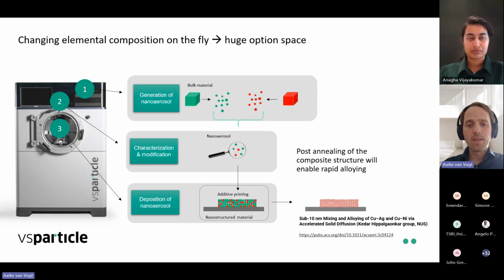One additional comment I would like to make is that we can print these nanoporous layers on almost any substrate. And the reason is that we build up these layers by using very small 2-3 nanometer particles, which by themselves have a very strong van der Waals force. And this strong van der Waals force will make them stick to any surface, but also to any of the other nanoparticles that you print. So we can print these nanoporous layers directly onto polymeric membranes, onto silicon wafers, onto copper foils, onto glassy carbon substrates, onto rotating disc electrodes. So that makes the process not only very material flexible, but also substrate flexible. In the case of John, we printed on these ITO-coated glass plates.